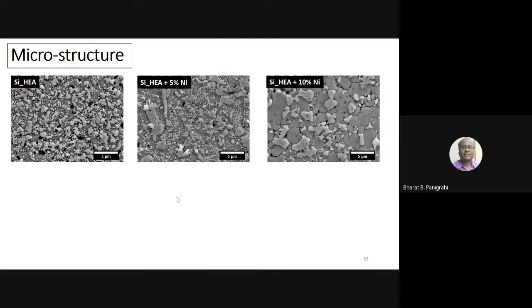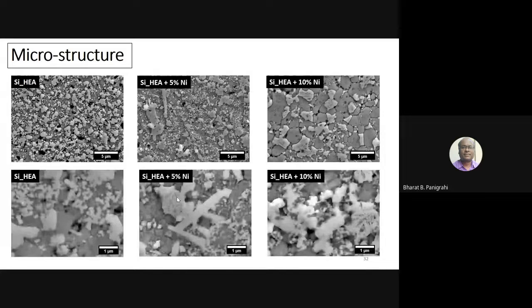These are simple microstructures. If you gradually increase the magnification to high resolution, you can see a lot of fine structures formed here. By adding the nickel, a huge amount of fine structure is formed. If you look under the microscope, you have huge laminar, needle and fibrous structures formed. The formation of this fibrous structure and fine needles, which are basically nano needles, essentially like nanorods, huge amounts of nanorods, has led to a massive jump in the strength. So it's a very simple but very effective technique to design an alloy with very high strength.